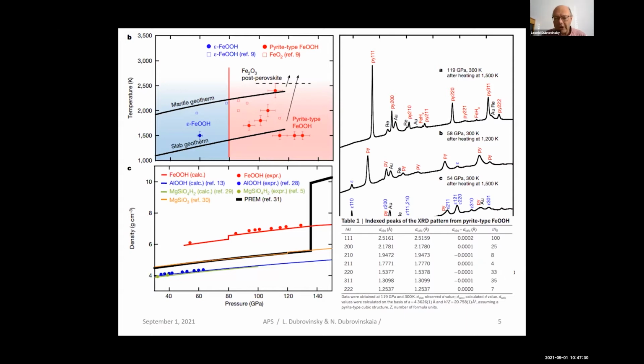Or FeOOH if you wish, and we will come back to this phase in a few slides. But what is even more interesting, not only did the qualitative assignment of this data lead us to the conclusion that the phase of iron oxyhydroxide is stable up to, let's say, 100 GPa and temperatures around 2000 K.